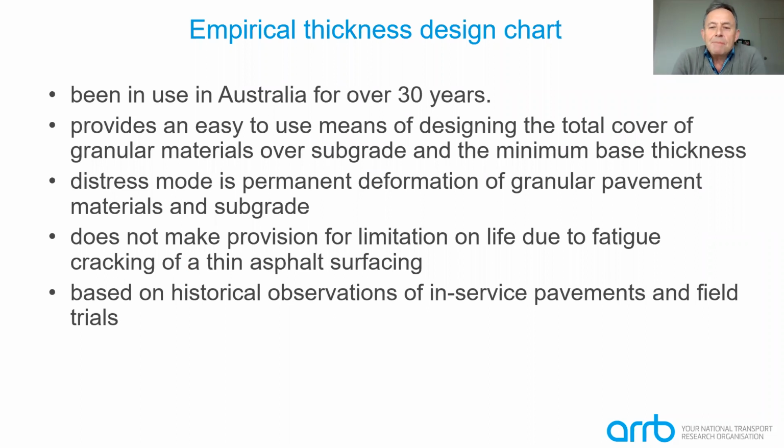So this chart provides a means of designing the total thickness of granular material over the subgrade, with some minimum base thickness requirements. The distress mode that we're designing for is rutting and deformation of the granular pavement materials and the subgrade. So we're designing for surface deformation, and that surface deformation could be a result of the granular layers deforming and also the subgrade and select fill layers deforming. That's the mode that we're designing for with the chart. There's no consideration of fatigue, either from thin asphalt surfacings or cemented layers, in this chart.